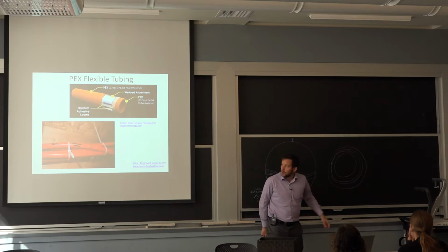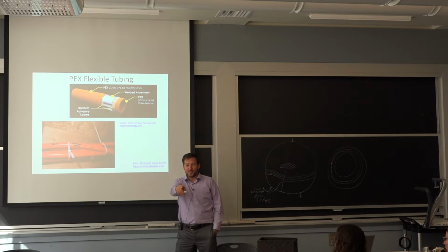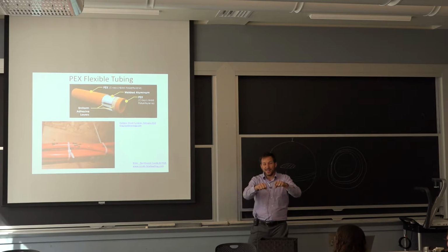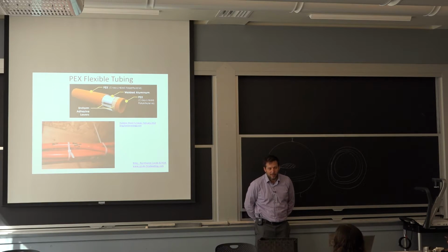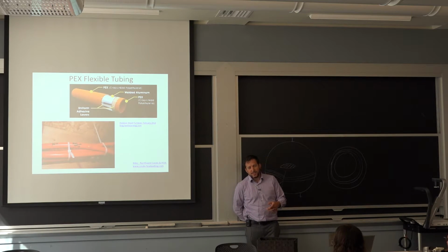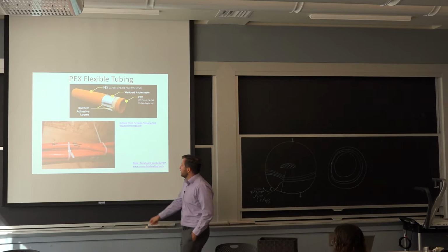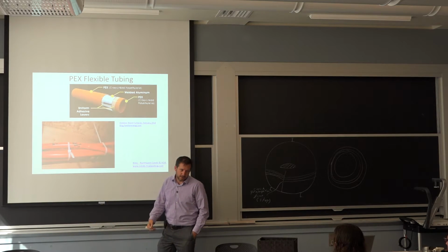So there was this purpose of the aluminum, but then the plumber said, hey, this pipe, I like it much better. First of all, if you have the aluminum core, if you bend it, it stays bent because the aluminum keeps the shape. So there's been this growth in the use of the product for potable water. The problem with potable water is now they had essentially oxygenated water going through it. And instead of having the resin last for the original intent of 20 years, it lasted a couple years and then started making these big blisters everywhere and leaks.